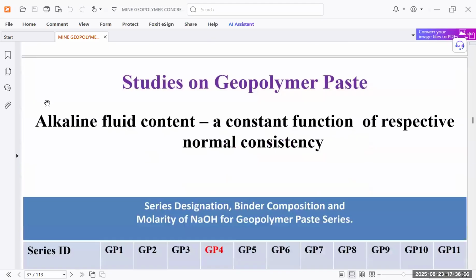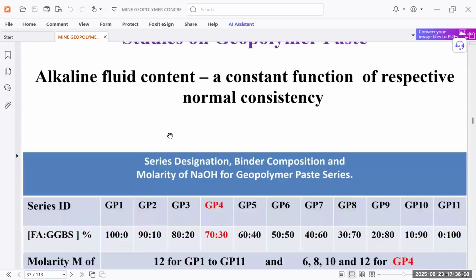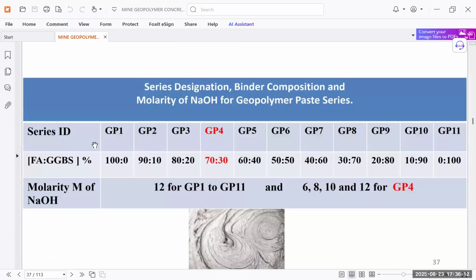So studies are going on. Alkaline fluid content is a constant function of the respective normal consistency. So, series designation, different trials we make: geopolymer 1, geopolymer 2. Here the fly ash to GGBS ratio is 100 to 0, and in this case, fly ash to GGBS will be 90 to 10. This is GP1, GP2. These are different trials, using different percentages of fly ash and GGBS.